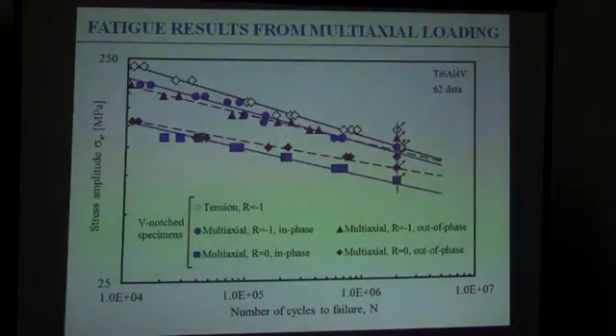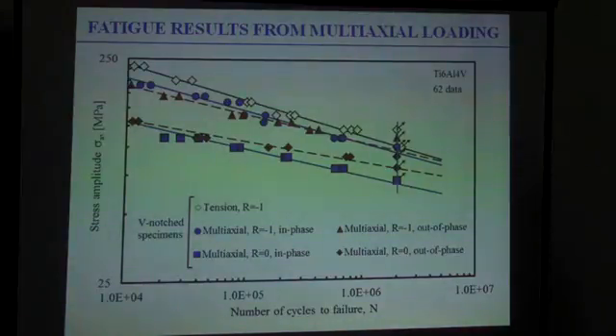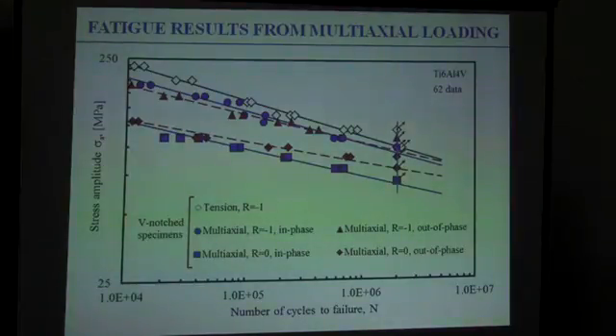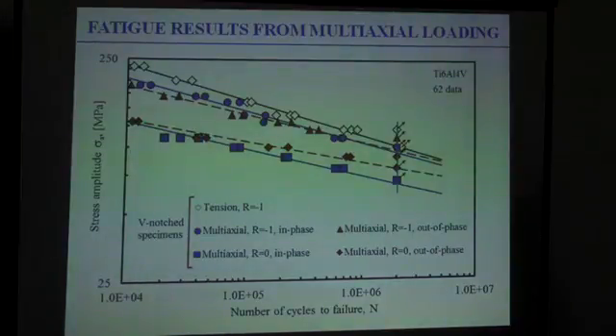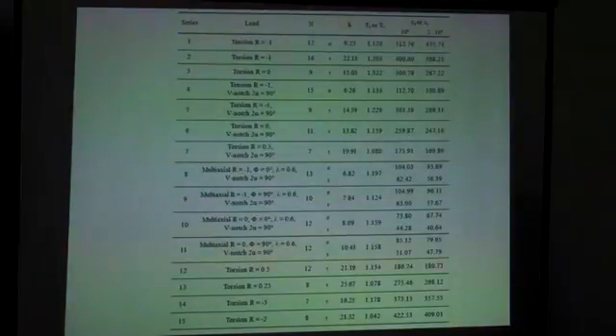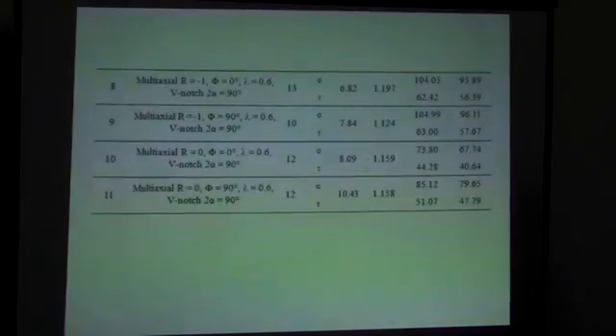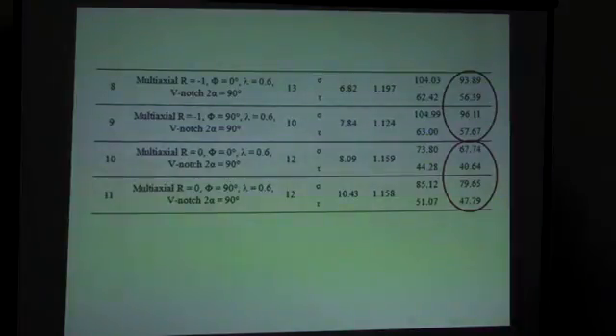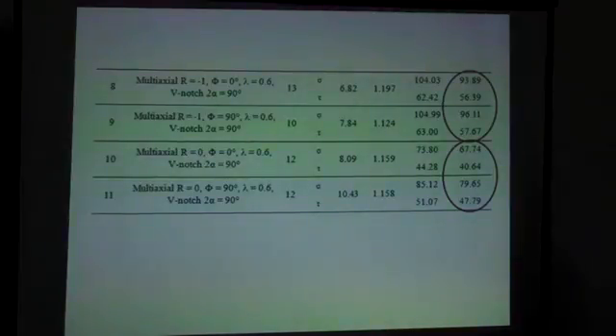And we have considered multiaxial fatigue tests, where we have combined tension and torsion with a biaxiality ratio, which is the ratio between shear stress and tensile stress, equal to 0.6. And these are the data with very large scatter and different behavior under different mode combinations. We have summarized all the data. What is interesting to understand is that for this material, the effect of out-of-phase loading is quite limited. In fact, if we compare the two cases of R equal to -1 and R equal to 0, we have almost the same fatigue strength in both cases. There is not a strong influence or reduction due to out-of-phase loading.